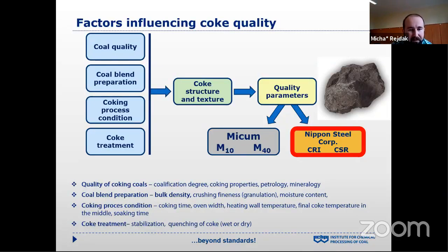Very important are coking process conditions like coking time, oven width, heating wall temperature, final coke temperature in the middle, and soaking time. The last but not least, the coke treatment is also important, because stabilization of coke on the conveyor belts during the technological system of the coke oven battery also influences the mechanical strength of coke. And also quenching of coke plays some role, because we can imagine when we spray the hot coke with the temperature of 1000 Celsius degrees by cold water, there is some tension in the material and some fissuring can occur. So it influences negatively the mechanical strength of coke.